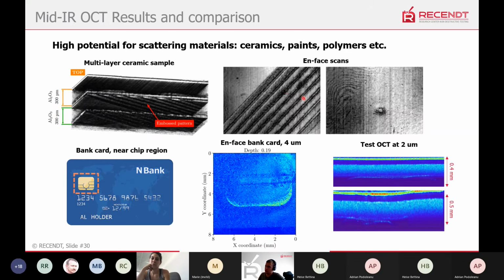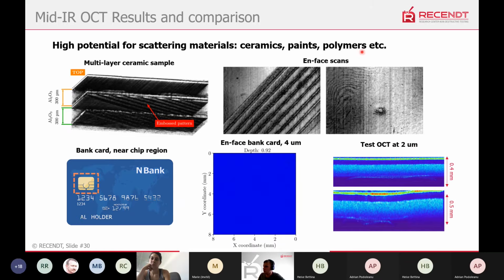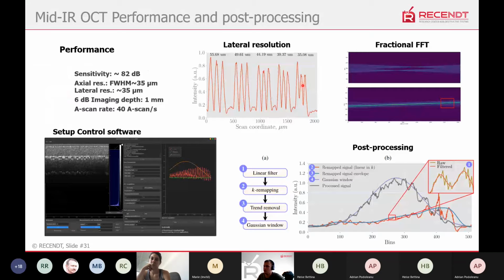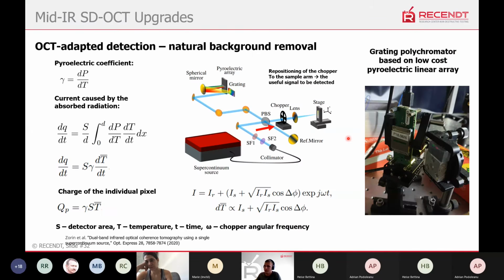Just some other results that we received a little bit later. Such a sandwich can be probed quite well. Also some defects can be observed, defects in this microstructured ceramics. So it worked well, and also test OCT imaging at 2 micron appeared. Then some post-processing algorithms, and I made a GUI for the system to operate it easily. This fractional FFT I tried for dispersion compensation, but I think it never was integrated, but it was quite interesting that Bettina offered. I think these were quite standard post-processing procedures. So then the system was upgraded.